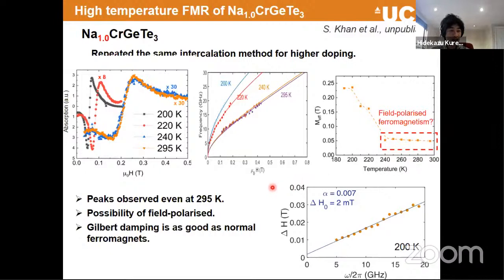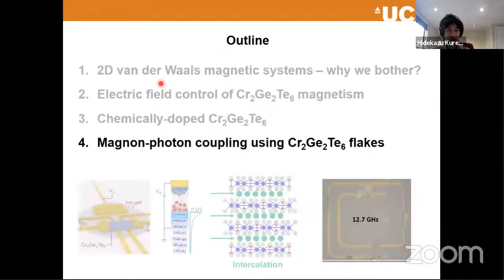Another thing I just want to quickly share is that the line width as a function of field, or frequency, can give us very nice encouraging news, because when you fit that with a linear fit, we can extract the Gilbert damping alpha, and this value is similar to what we observed in the 3D transition metal cases. So in that case, we can use these materials. I mean, this is just one example, but these van der Waals systems are not bad to use for spin wave or dynamic experiments. So that's that.